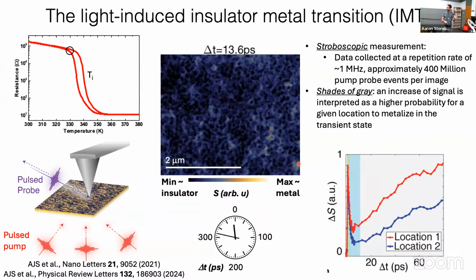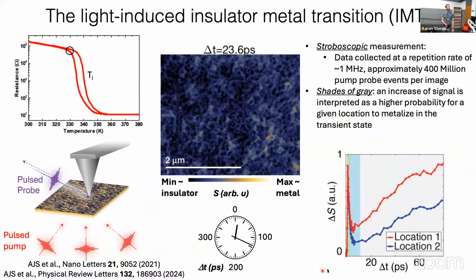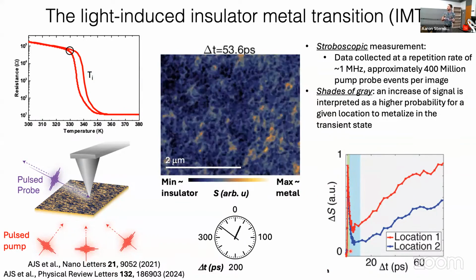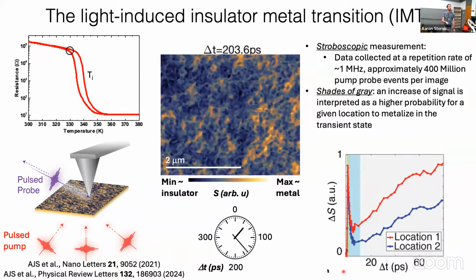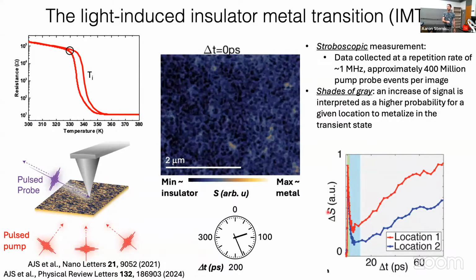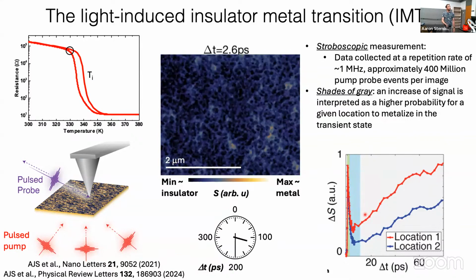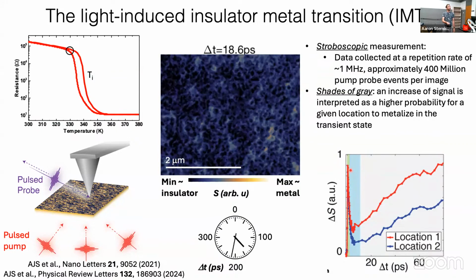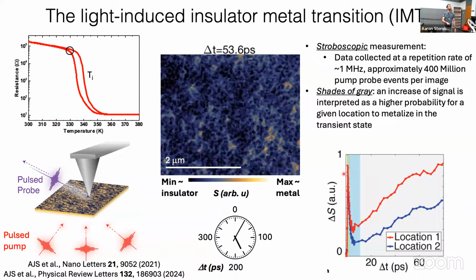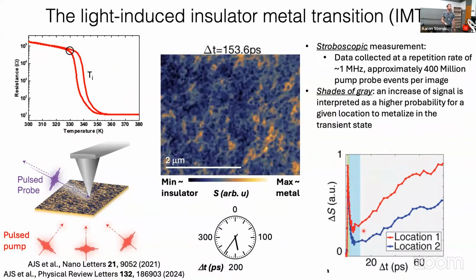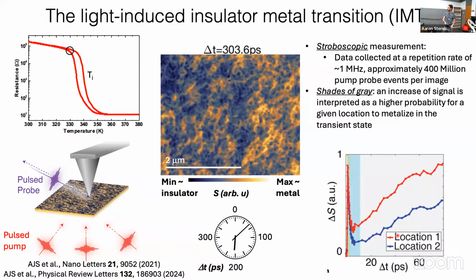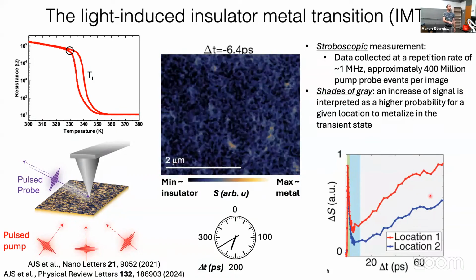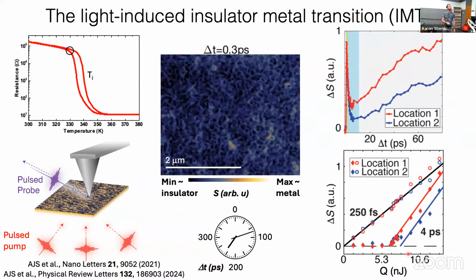So while this movie is nice to look at, you can perhaps see a little bit more detail if you just focus on line traces. So how the system evolves as a function of a single parameter at a single time. So first, we can look at the change in scattering amplitude, which you can think about as suggesting this conductivity, as a function of the pump probe time delay. First, the scattering amplitude rapidly increases, and then there's a relaxation on a sub-picosecond timescale before there is a follow-up growth. And it's this follow-up growth that is inhomogeneous.